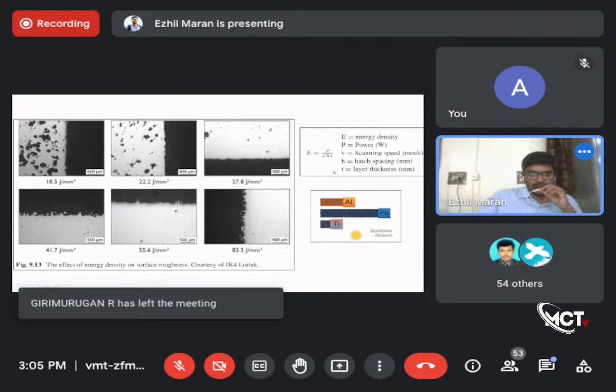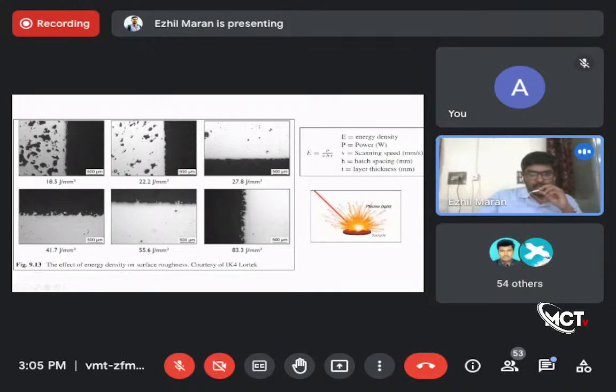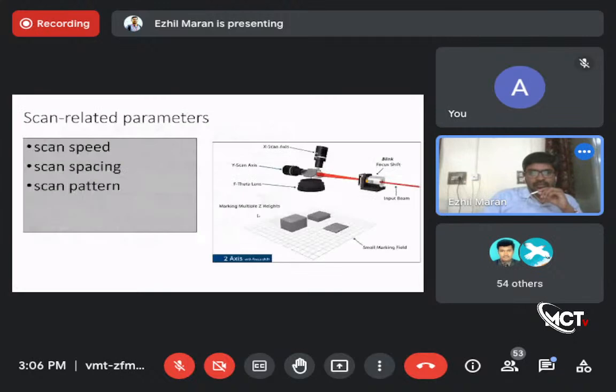Slowly, the energy is increasing and the porosity is reduced. At a high energy of 83.3 joule per mm cube, the porosity is completely eliminated. But it creates another issue. The surface is not smooth. The surface contains a lot of roughness. So at lesser energy, the porosity is very high, but the surface is somewhat smoother. If you increase the energy, slowly the porosity is reduced, but the surface is rough. So you have to keep in mind what is the appropriate energy you have to use, and what is the requirement.